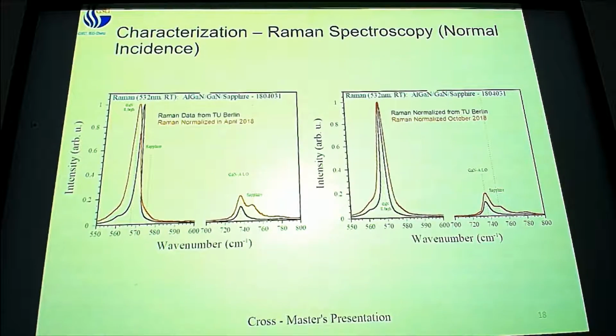Is it more advantageous in this higher wave number area? Is that why you can see that sound? I would actually argue the opposite. We do not really care about the sapphire peak. It means nothing to us. It's just the substrate. The things that we do care about, talking about this higher area here, is this peak over here. This is actually AlGaN, so it's aluminum gallium nitride. And what that means is that this A1 peak is actually shifted for the top layer, this AlGaN layer on top of our gallium nitride. So as long as we can see that, we're good, because that means we're seeing the top surface of our sample.